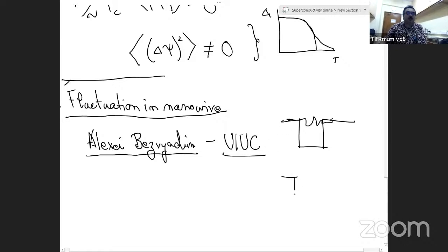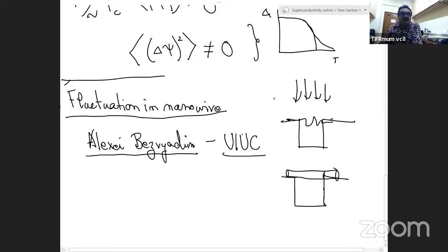The DNA has no biological implication here, except that it's like a thread, or you can put a carbon nanotube here, and then he would deposit a superconductor by evaporation, so that this superconductor would get deposited on this carbon nanotube or on this DNA. Often that superconductor was molybdenum germanium, and this would become a superconducting nanowire.